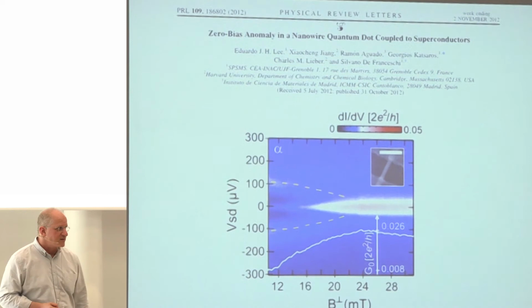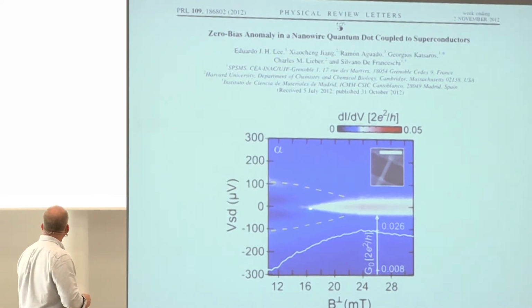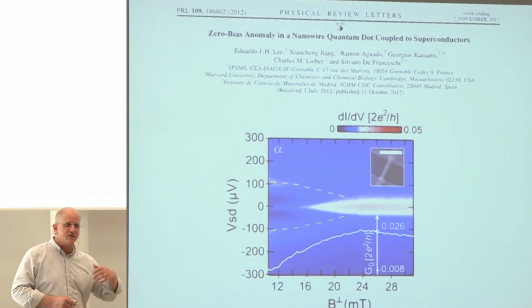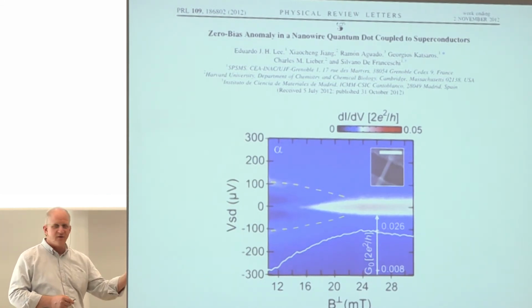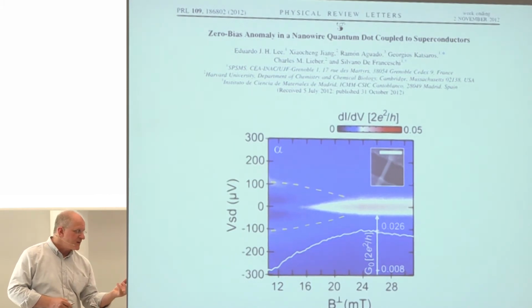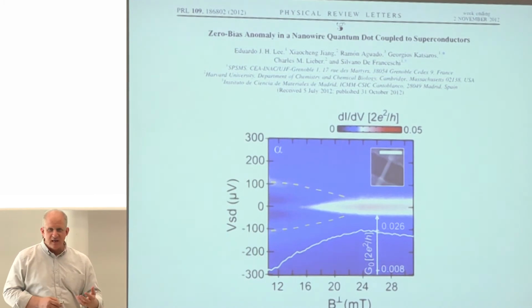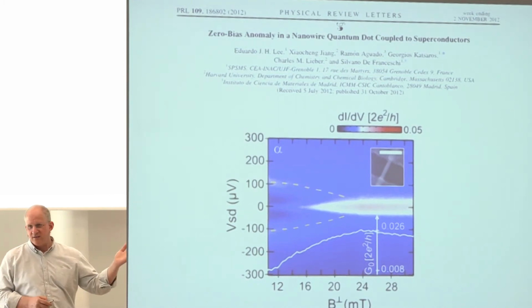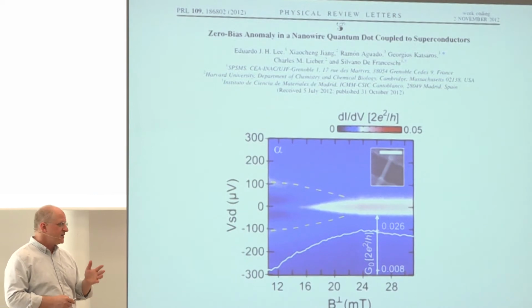This peak is the Kondo effect. And it appears at finite magnetic field because you have to destroy the superconducting state before there's enough normal carriers in the leads to have a Kondo effect with a bound spin on the dot. So there is physics that will produce a finite field onset of a zero bias peak. It's not sufficient to say that's the Majorana. And like the other experiments have done, you have to look at field angle, you have to look at different materials, etc. So it's passing the test, but not because there aren't things out there that are disguising themselves as Majoranas. And so, like with any experiment, care has to be taken.